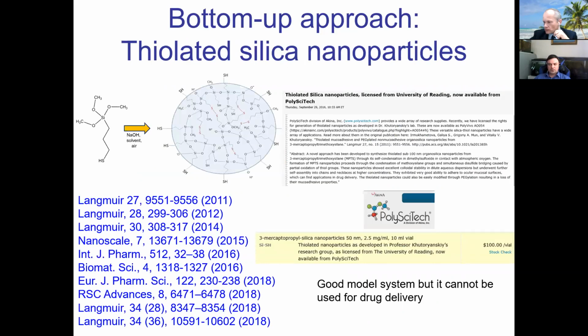And one of the first attempts to do that was to play with thiolated silica nanoparticles. So we pioneered the synthesis of these particles. There's a number of thiolated silica papers that were before our study, but we changed the synthesis conditions slightly, and we managed to hit into the area where the particles are formed of particularly small size and high yields. So we did a lot of work on these particles and demonstrated that they are highly mucoadhesive.